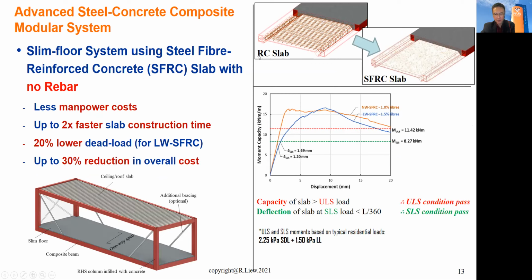And for example, this is a conventional RC slab for a module, which we propose to replace with a steel fiber reinforced concrete slab. And we did a test of this SFRC slab and compared with lightweight and normal weight, and it has an adequate moment capacity versus deflection curve. The capacity of the slab at ultimate easily exceeded the ultimate limit state capacity, and the deflection of the slab at SLS is within the limits, based on a typical live load of 1.5 kPa and the superimposed dead load of 2.25 kPa.